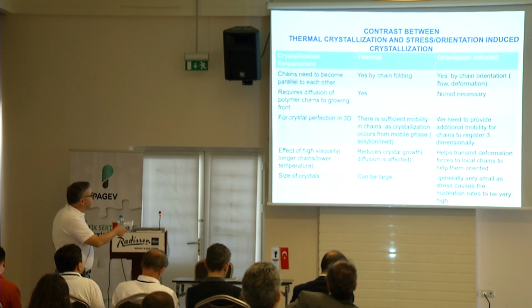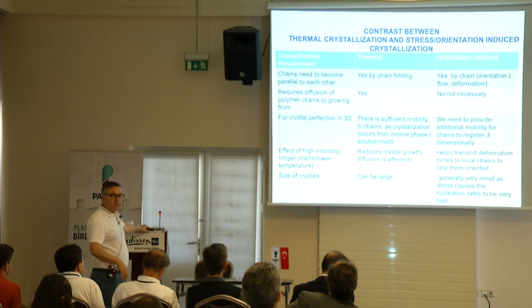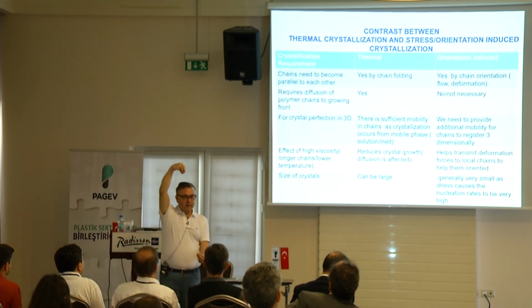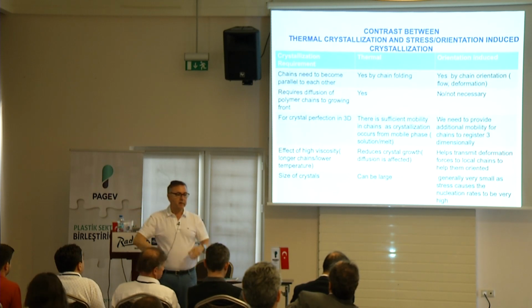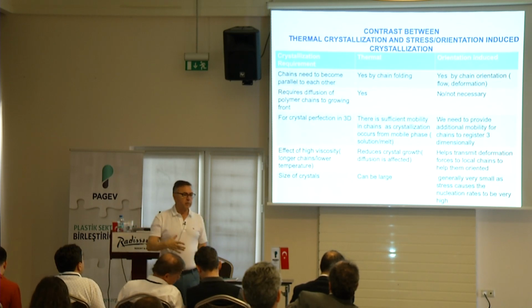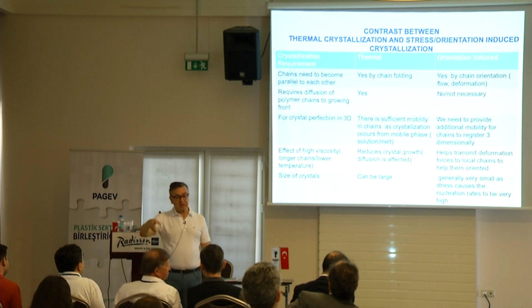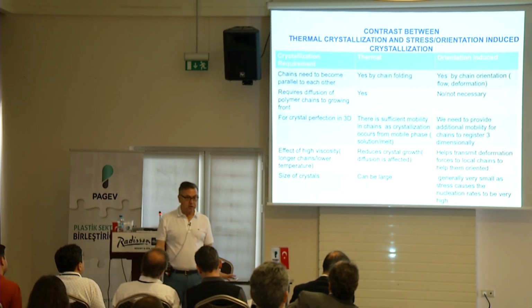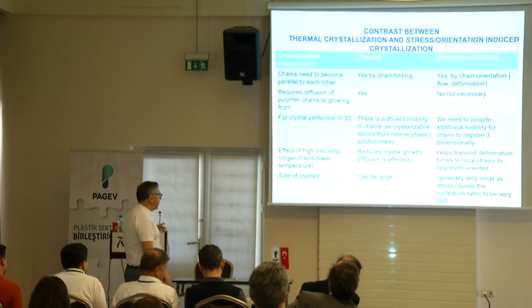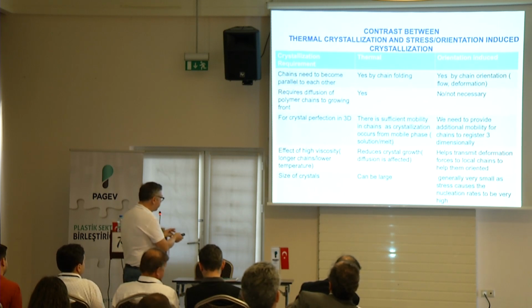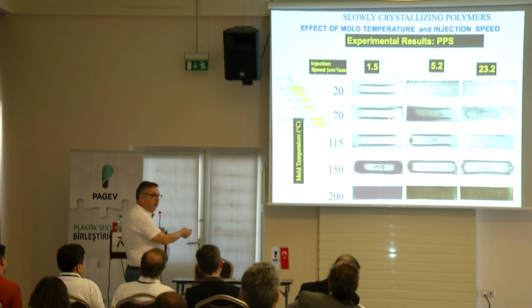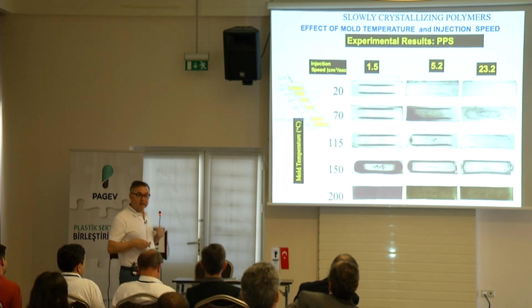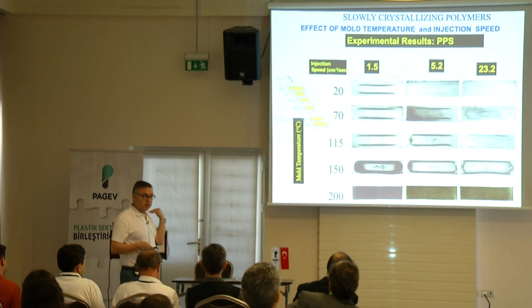Does it require diffusion of polymer chains to the growing front? For orientation-induced, not necessarily. You don't need to diffuse anymore because you're orienting them locally. They don't need to come from far away. So if you have diffusion, it's going to help. If you don't have it, it will do just fine. And as you saw in the core of that previous observation, there's plenty of time for diffusion, but it doesn't crystallize because thermal crystallization is turned off.